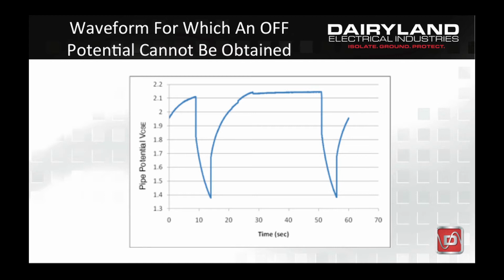The real clue that something is wrong here is that an off potential can theoretically not be more than minus 1.2 volts when measured with respect to a copper sulfate half cell, commonly shown in the literature as a capital letter V with a subscript CSE. If the off potential for this waveform were measured at a typical 300 millisecond measuring delay time after current interruption, the off potential of about minus 1.8 volts would certainly indicate that something is wrong, since it is significantly greater than the minus 1.2 volt limit.